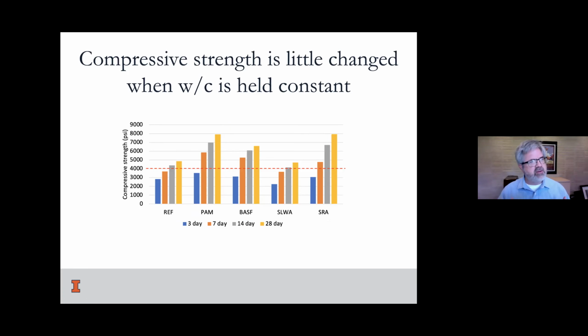I guess I would say there's some argument about having a more homogeneous microstructure. But at any rate, there's not a reason to think that somehow the use of this SAP is going to create a spiral of problems with strength and so forth. We think that it'll be conservative, and your experience with strength should be just fine. But if you want to target a strength, I think we go back to cement mix design basics. We design for the strength based on a water content in the mix, the water cement ratio, and so on.